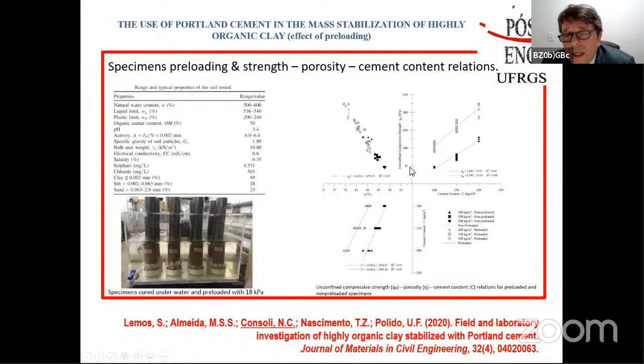We can see here that after a period of time, we have tested the unconfined compressive strength versus the amount of cement, 100, 150, and 200 kilograms per cubic meter. We have checked that without preloading, we have this kind of trend. And with 1 meter thick preload, which means 18 kilopascals, we have this increase from here to here. Besides, we have measured the porosity that we have had in these specimens.